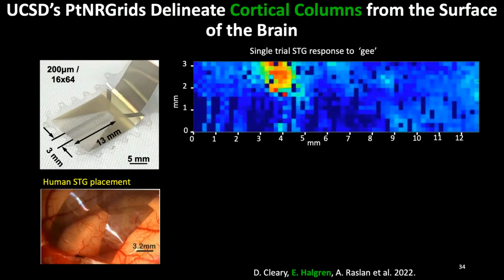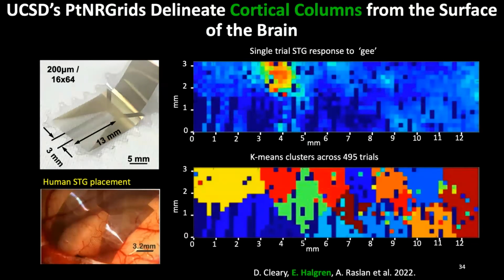So here we're looking at the high gamma response as a function of space for the phoneme G. And you can see that the phoneme evokes activity within, again, a millimeter type space across this grid. And when we do this across many trials and across many phonemes, you start seeing a mosaic distribution of where phonemes are decoded on the superior temporal gyrus.